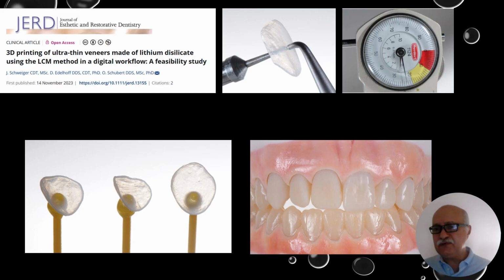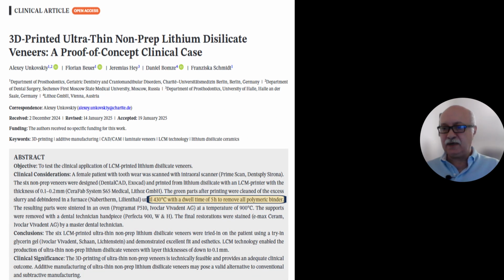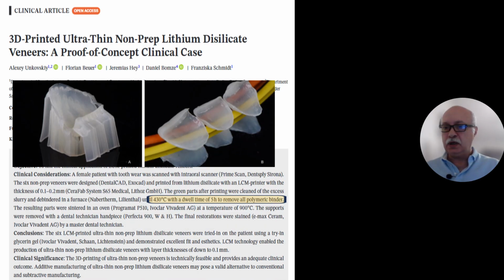A major advantage of 3D printing lithium disilicate by using the LCM method is obtaining ultra-thin restorations, which is very difficult to achieve in the conventional method. On the other hand, an important disadvantage is the prolonged and sensitive debinding method, about 5 hours.